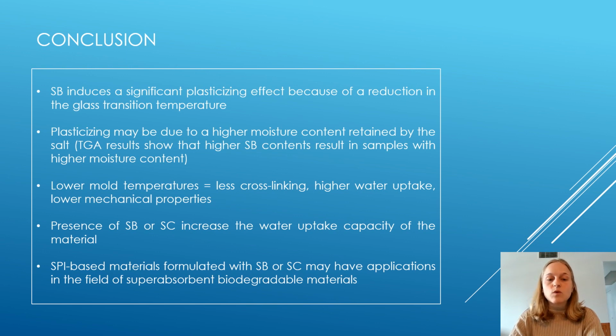It also increases the water uptake capacities, which peaks at around 2.5% salt content. After replacing SB by SC, they found out that water uptake increases in the presence of SC. Indeed, it reached an absorption capacity of 36 times its own weight. So, soy protein-based biopolymers formulated with SB or SC could very well be used as a biodegradable superabsorbent material.